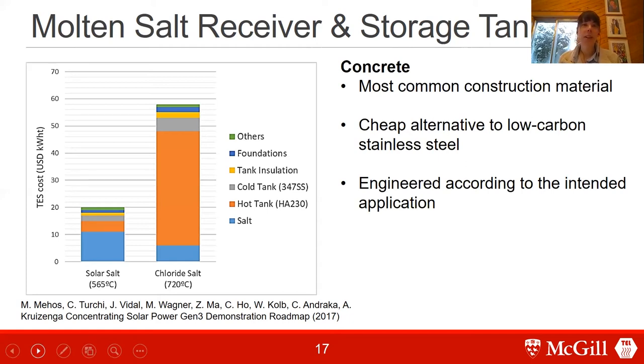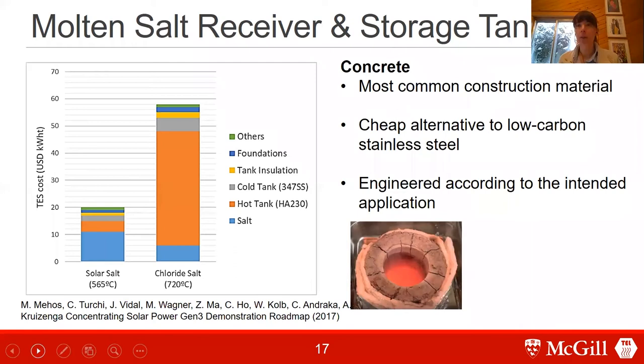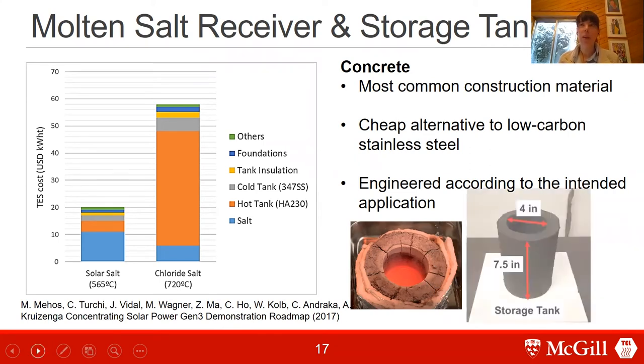So you could see here, if we just use regular concrete with chloride, this is a little concrete tank that we have in our lab and it's filled with chloride salts. If we just use regular concrete, the thermal stresses are going to cause it to crack, as you can see here. So we're starting to develop these new concrete materials that could withstand these much higher temperatures and these corrosive environments. So we've been developing these little tanks in the lab that we've been testing under various conditions.